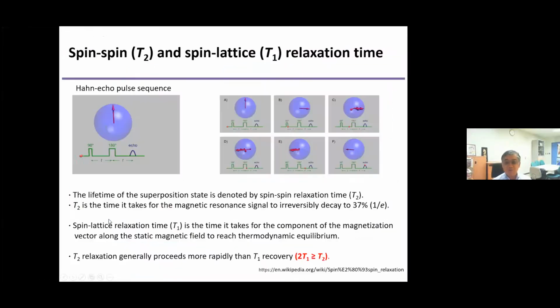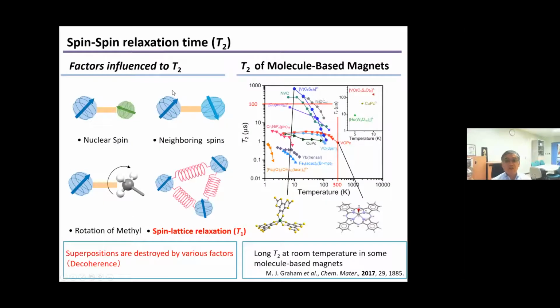So this is the definition of spin-spin relaxation time T2 and spin-lattice relaxation time T1. The important point is that double T1 is larger than T2. This is a limitation, a very important condition. As for the spin-spin relaxation time T2, the factors inversely related to T2 are the nuclear spin, neighboring spin, rotation of methyl, and spin-lattice relaxation time.